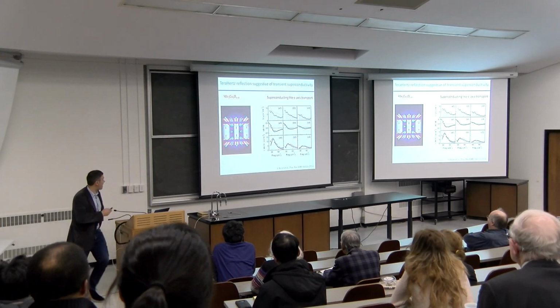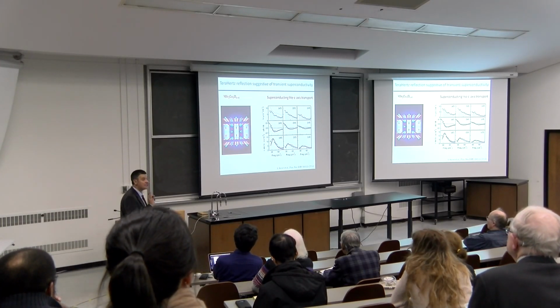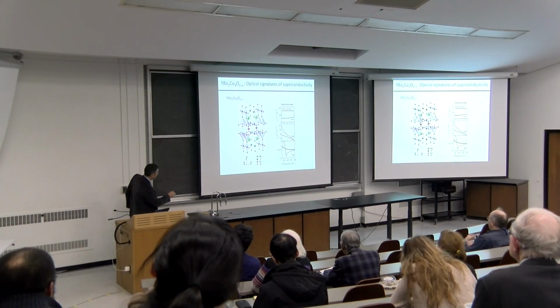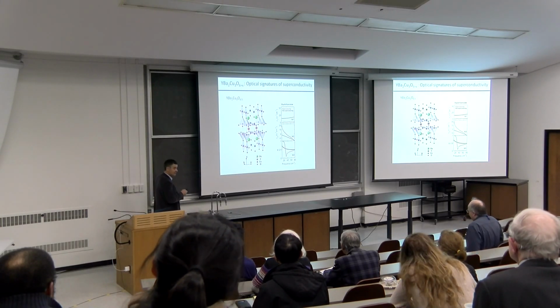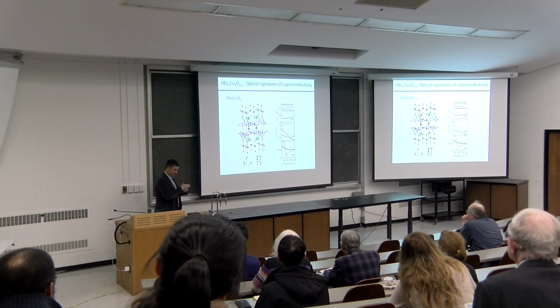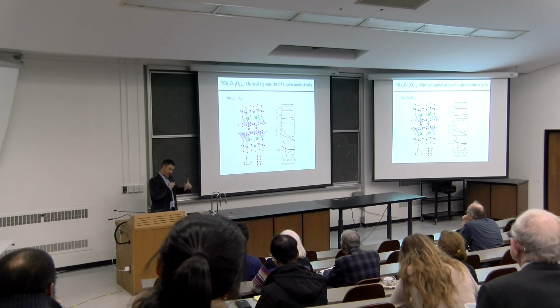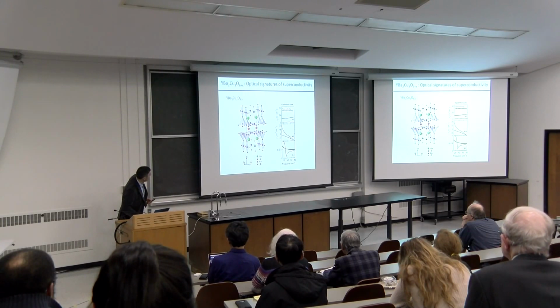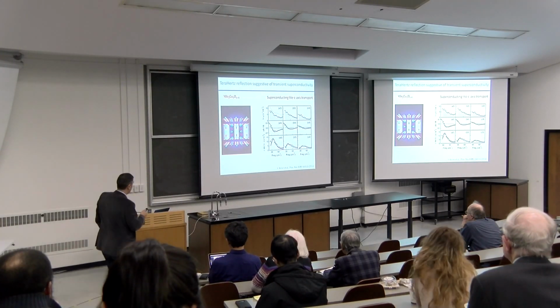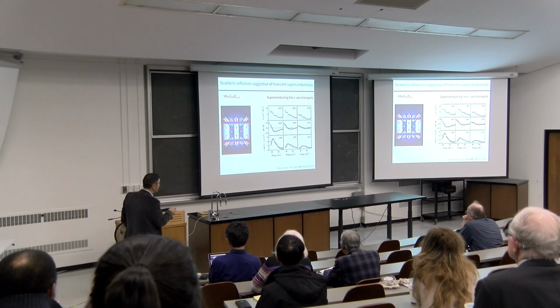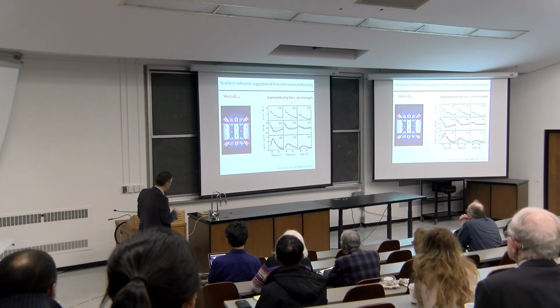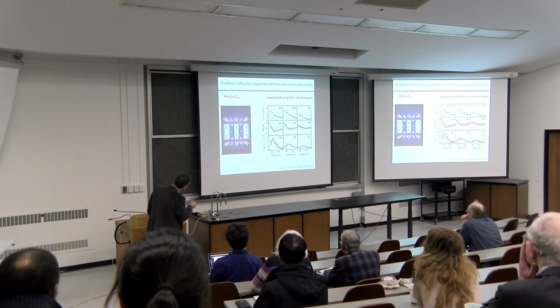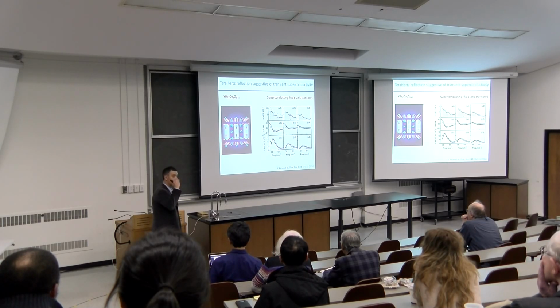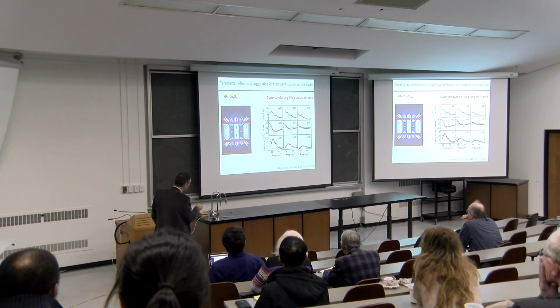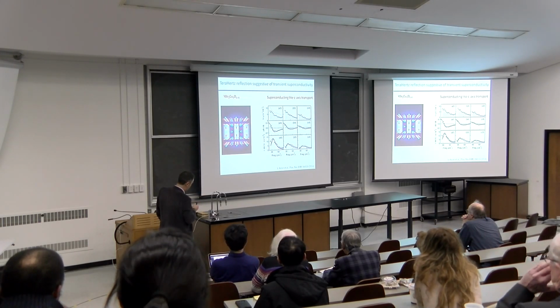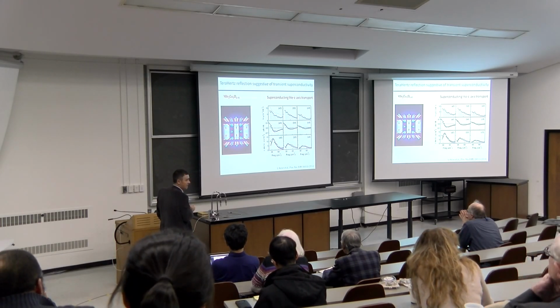So what we found, at least at the beginning, I am plotting now the changes in conductivity. So I'm taking now the black state, which is the non-superconducting state, and I'm going to show specifically changes in conductivity, because the way we did the experiments at the beginning was we had to rely on sort of differential measurements. And what we found was at least something that was convincing enough for us, where we showed that, for example, the changes in the imaginary part of the conductivity were indicative of a 1/omega-ish response. And for comparison, this curve gives you the change between high temperature and low temperature at equilibrium. So we could generate a change in sigma 2 that was suggestive of the same properties of a superconducting state, but maybe about half or 2/3 as big as what one observes at equilibrium.